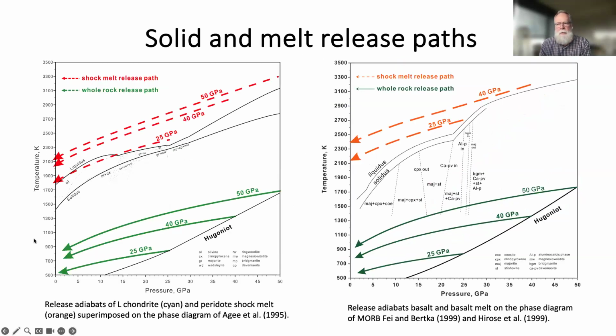So the next thing he did was to calculate release paths. What would be the release path for a bulk sample shocked to 25 GPa? The release path is concave downward like this, and this is the release path for 25, for 40, and for 50 GPa. So this gives us some constraints on what our quench paths can be. He also did release paths for liquids. If we had a total liquid at 50 GPa up here starting at about 3200, this would be the path. You can see that the liquid release paths are very similar in slope to the melting curve.